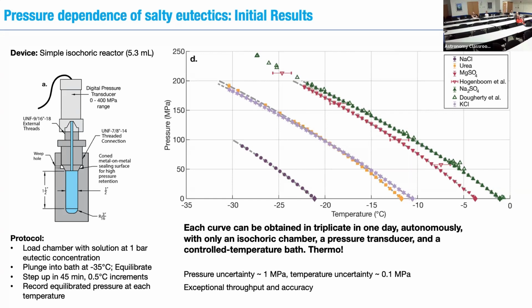And then also really high time efficiency in these measurements. For each of these curves, we just take this chamber with the given solution, put it in some automated bath where we cool it down and then warm it in controlled steps, letting it stabilize at each temperature. We read the pressure, that's it. So I can run, say, 3 of these at a time. I can put it in at 5 p.m. when I leave, and when I come back at 9 a.m., I have this fully constrained curve.